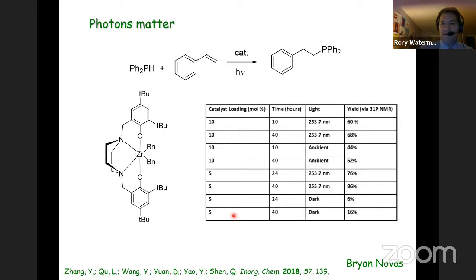The photolysis is something that extends beyond the zirconium geometry. And so there's been some nice follow-up zirconium catalysis reported a few years ago. So there's a handful of different ligands that were utilized. And I simply draw your attention to this phenoxide derivative because it is geometrically different than our triamidoamine zirconium compound. So now we're talking about same metal, different geometry. And in this case, we can see substantial acceleration by irradiation of these compounds that were reported by others in comparative times. And so it's really about activating zirconium. It's not special to that ligand set.